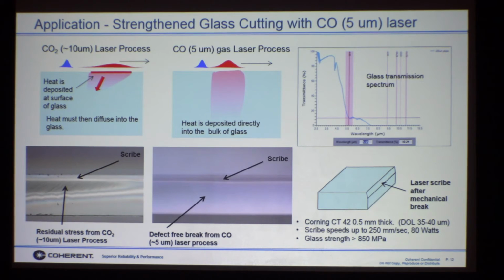The beauty of the CO laser is, now you can look at the spectrum again, sorry it's a little smaller, but now you see that at 5 micron, the glass doesn't absorb 100%. So the light at 5 micron actually penetrates deep into the glass. It's deposited into the glass rather than being absorbed 100% on the surface the way it is for CO2. And that allows you to control the amount of heat. Depending on the glass, the penetration is anywhere between 50 and 80 to 100 microns deep into the glass without diffusion. So now you're processing at the speed of light, basically. Your scan speed, the control over this line, all of this becomes less important.